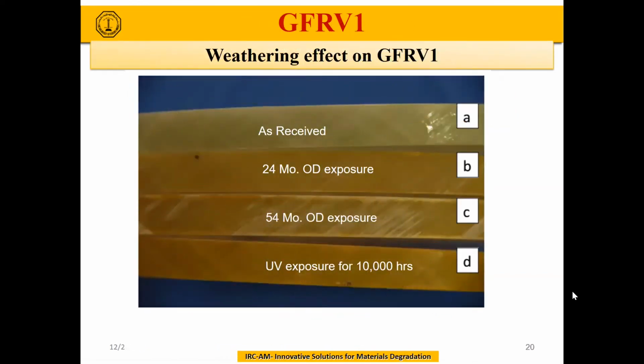First of all, let's look at how the weather affects the color of the material. What you see here is the greenish, yellowish color of the as received pipe. After 24 months, you can see that it starts to discolor and becomes brown. And then after 54 months, you can see that fibers are coming out. So the layer of epoxy or the layer of vinyl ester starts to degrade.